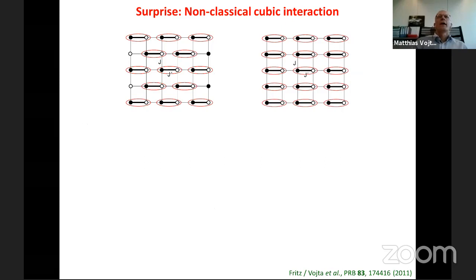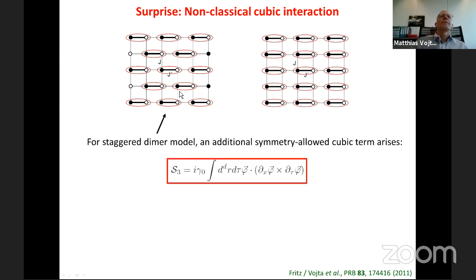Okay. Although this theory is well understood, I just want to report on a little surprise which we came across a few years back. Namely, there were numerical simulations which studied the critical properties of such systems, and they found that the system here on the left-hand side behaves differently from all the others. And that was a surprise, because usually one would expect that universality dictates that all of these coupled dimer systems behave in the same way.